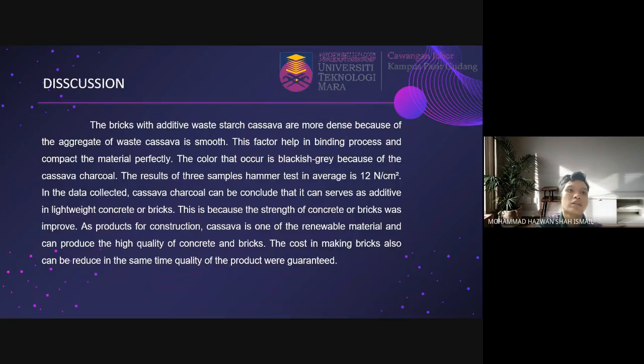The bricks with additive waste starch cassava are more dense because the aggregate of waste cassava is smooth. This factor helps in the binding process and compacts the material perfectly. The color is blackish gray because of the cassava charcoal. The result of the 3 samples hammer test in average is 12 Newton per centimeter square. From the data collected, it can be concluded that cassava charcoal can serve as an additive in lightweight concrete or bricks. This is because the strength of the concrete or bricks was improved. As a product for construction, cassava is one of the renewable materials and can produce high quality concrete and bricks. The cost of making bricks can also be reduced while the quality of the product is guaranteed.